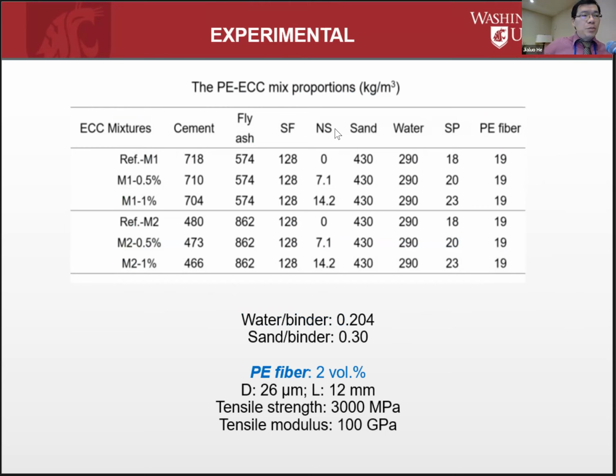Group one, M1, you can see has a little bit of ash, but group two, however, has a lot more fly ash. So it's a high volume fly ash binder because you have more fly ash than cement. And unintendedly, you'll find the self-healing behavior is much better. Not planned. We were just trying to use a greener binder, more sustainable binder. But in the end, actually, this one works really well in terms of self-healing.